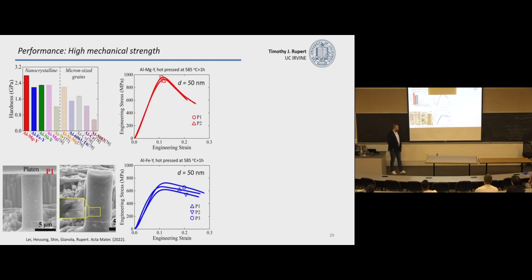And to put that into a reference that we might understand, these marks here in gray are what you would get for the yield and ultimate tensile strength of 7075 T651 aluminum, which is the strongest aluminum you can buy industrially off the shelf right now. So we're getting multiple hundreds of megapascals higher in strength.